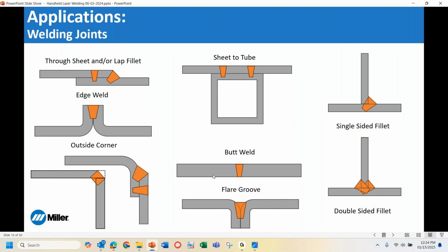Now, outside corners, we would typically want to provide some sort of a break on that component, so we definitely have a backer behind there, because the laser energy is so efficient at penetrating into the material. If we have a gap between the two parts, that laser energy can cause excessive penetration or essentially shine through the part. When we look at a structural member in a lighter application, sheet to tube.